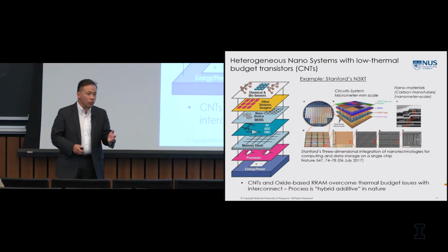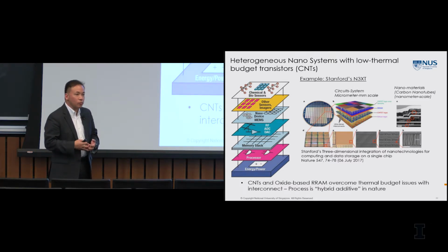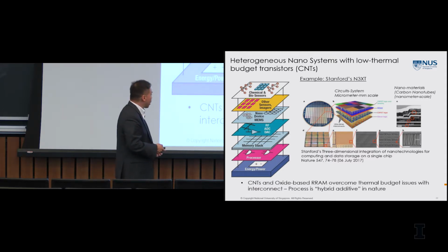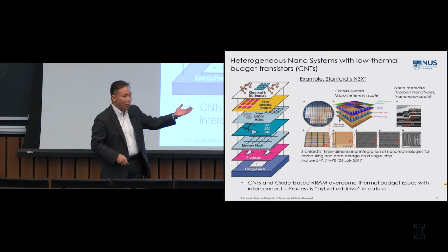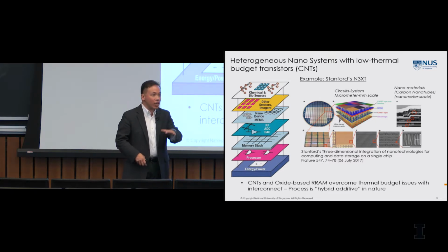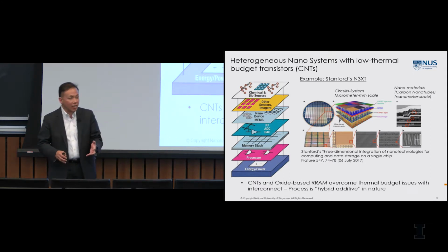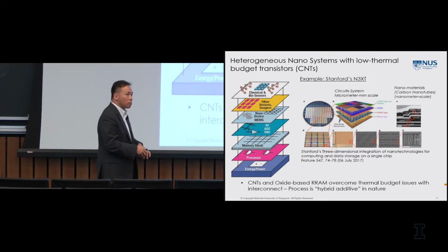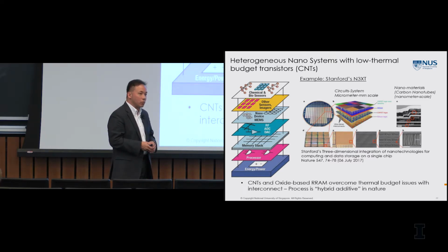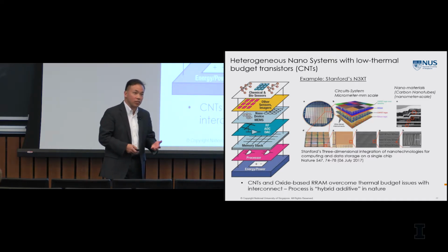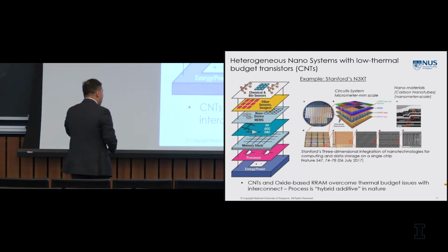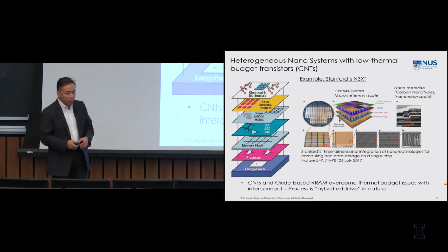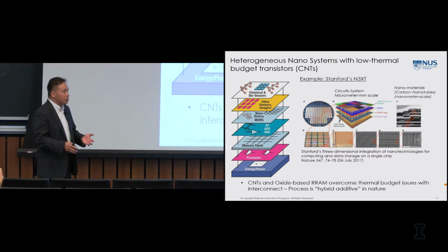And the reason they can do that is because carbon nanotubes are not silicon. They're actually additive-based transistors. They are processed at a much lower thermal budget. They are grown at a high temperature, but they are transferred onto the chip itself. So they are not like silicon, where it's processed on chip, where you need to subject it to high temperature, and hence it doesn't affect the circuit below. So I had discussions with Subhasish Mitra and Philip Wong, who did this work, and that's the main thing.